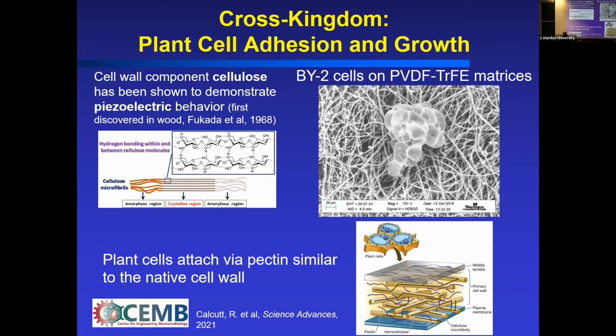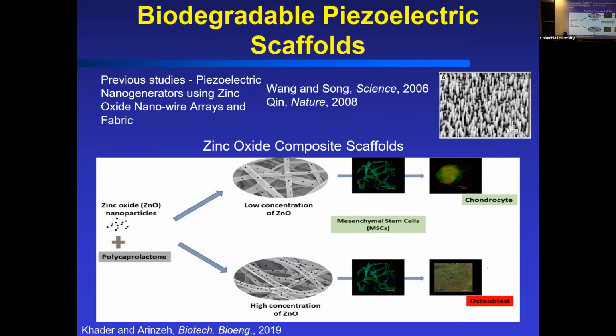And so what's interesting to note is that cellulose does have piezoelectric behavior. So these scaffolds try to mimic that type of phenomenon of the plant cell wall. And so plant cells will readily attach to these substrates. For us, we like to push forward with the development of these materials. Again, for application, we may not want to use those non-degradable fluoride compositions. And again, we're inserting these into the knee.